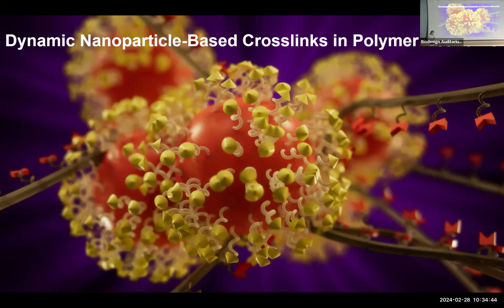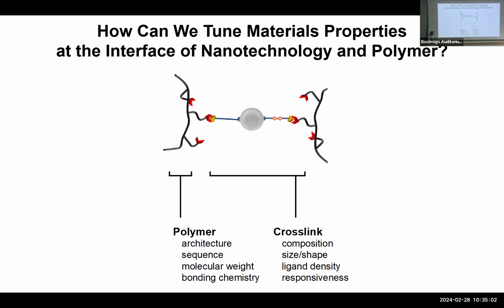Most of the previous methods in assembling self-healing composite materials either attach nanoparticles or polymers directly onto the nanoparticles. But these methods don't really allow you to control the number of binding events, and we think that is one of the important parameters to control for polymer nanocomposites. So instead of directly attaching these polymers onto the nanoparticle surface, we want to detach the core of the nanoparticles from the interactions. So we functionalize these nanoparticles with short ligands that have a binding moiety at the end of those ligands.